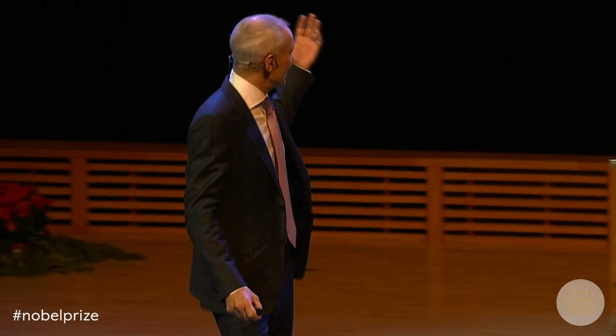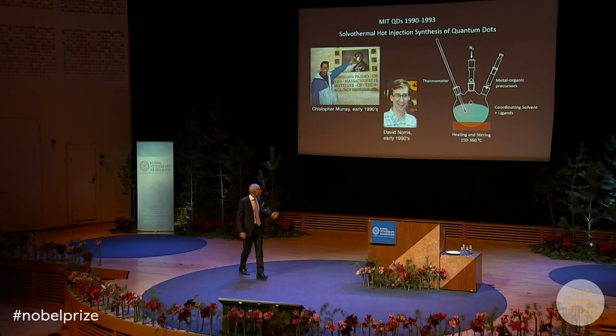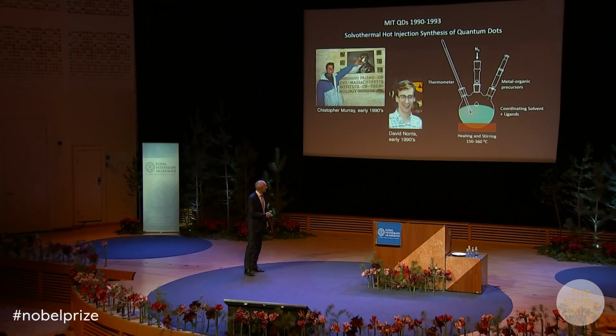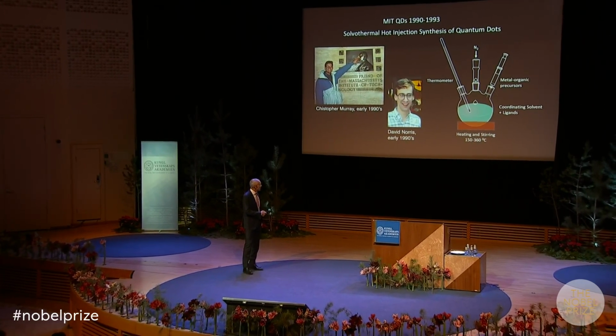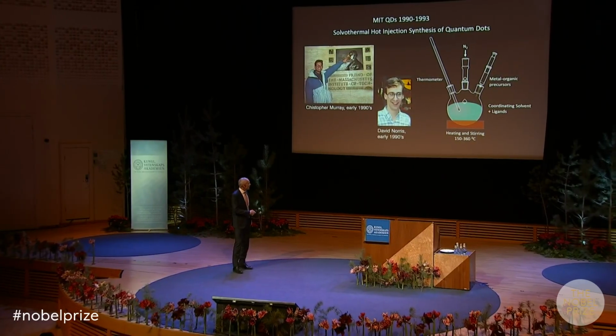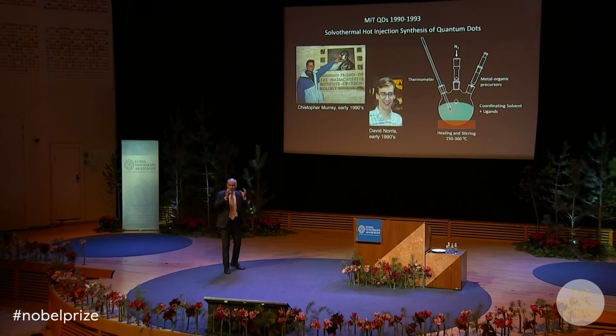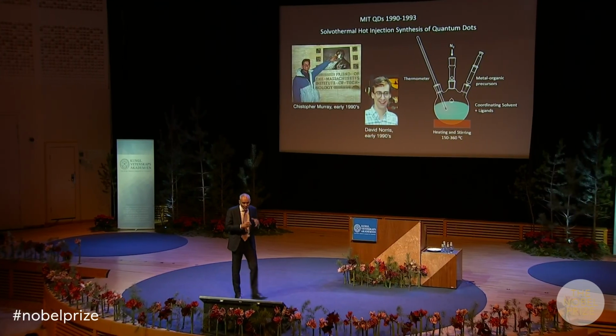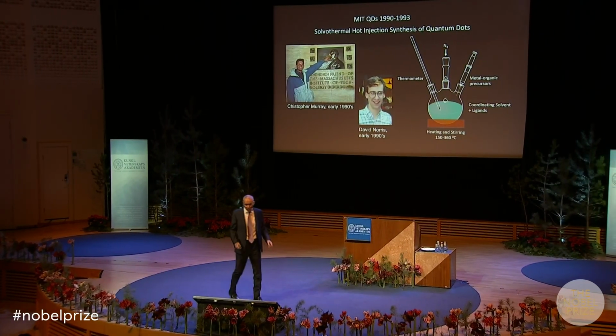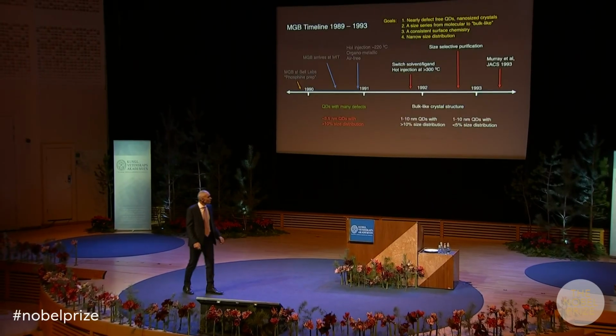this is a picture of Chris and David from that time here. We introduced the precursors rapidly through a syringe here into a hot solvent that contains the surface molecules that slow down the growth and provide a uniform surface of the particles.